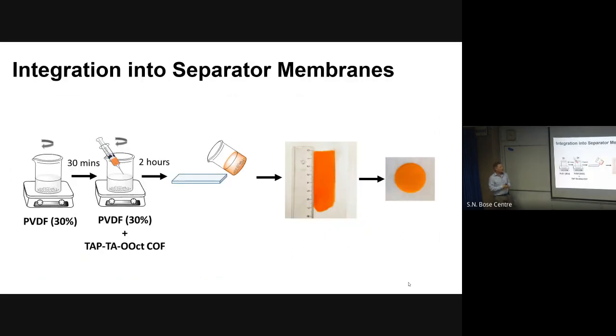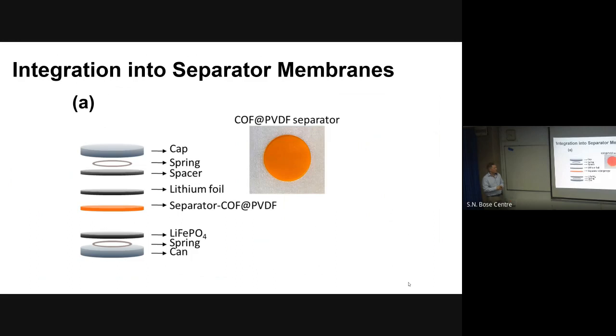As a very small proof of concept that there's some benefit to having these sheets, we integrated them into separator membranes, which we put into a lithium-ion battery type setup. We have a PVDF solution in DMF, and then we added some of this octyl functionalized material. Then we drop cast the ink that we made with PVDF and the material onto a substrate, and by the doctor blading method, we generate this nice film, and then we cut out membranes that we could put into a lithium-ion battery.